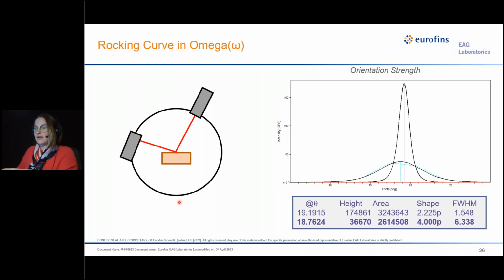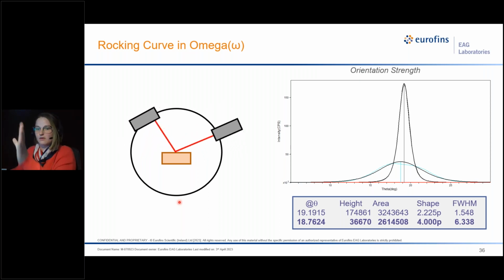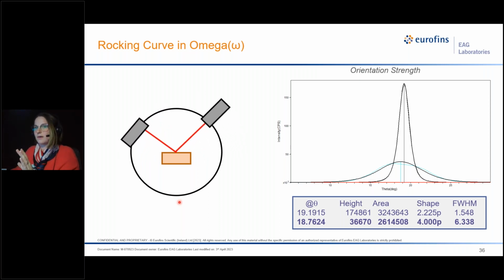So in the case of a rocking curve, what this is going to tell you is that if you have a very broad rocking curve, that means that you have very little texture or no texture in your sample. But if you have a very sharp peak, that means you're very textured, because all of the crystallites are pointing in that same exact spot in omega. And again, that's how the omega curve collection is going to work.